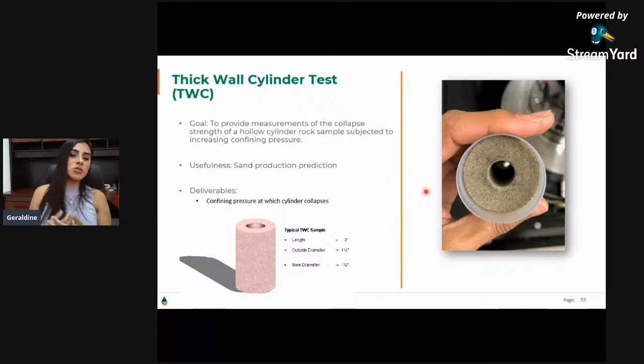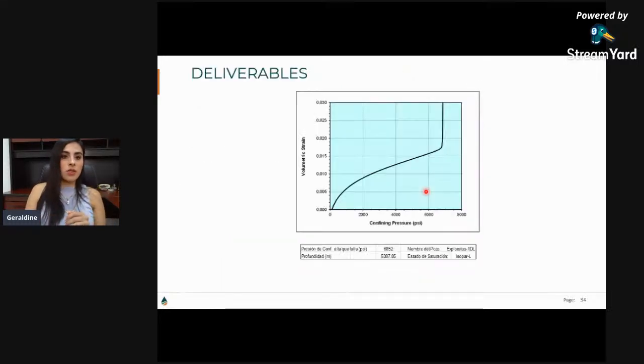The goal is to provide measurements of the collapse strength of a cylinder with a hole in the center in order to predict sand production. This is the main usefulness of this test. And the deliverable is the confining pressure when the sample fails or collapses. It looks like this, the plot of the test performance. Here is the point where the sample collapsed, or the hole in the center of the sample collapsed, and the confining pressure is here where the sample fails.